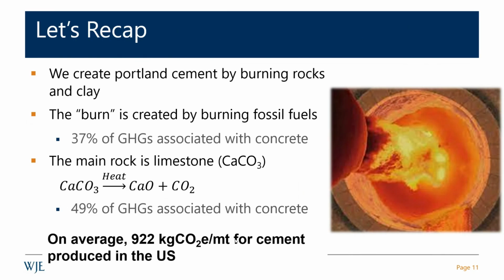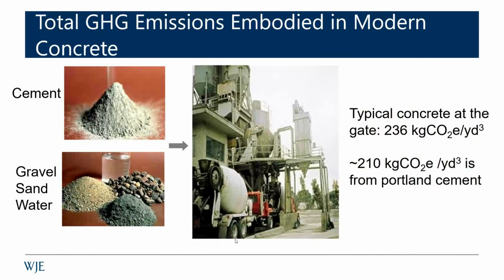And so, on average, roughly we have 922 kilograms of CO2 per metric ton of cement that we produce in the United States. When we translate this to our typical concrete, and this is on average from NRMCA's numbers, you're looking at basically 236 kilograms CO2 equivalent per cubic yard, a strange metric, but that's always how it's done. It's the one time where we use metric and English units in one measure. And almost 210 kilograms of that CO2 is from the Portland cement.